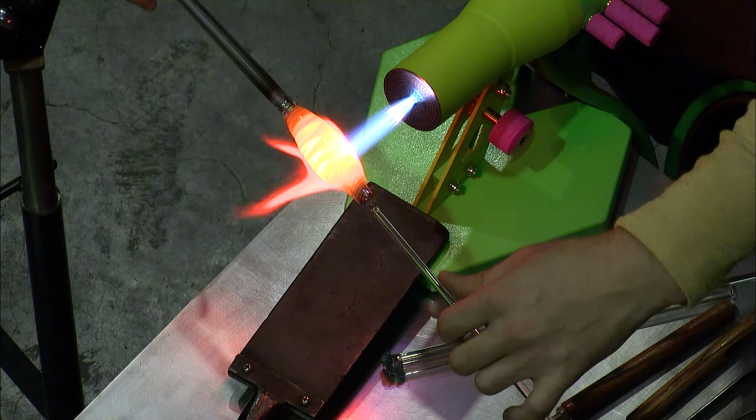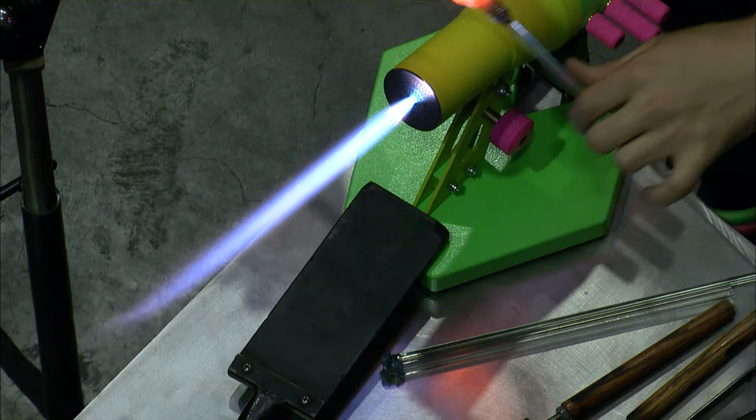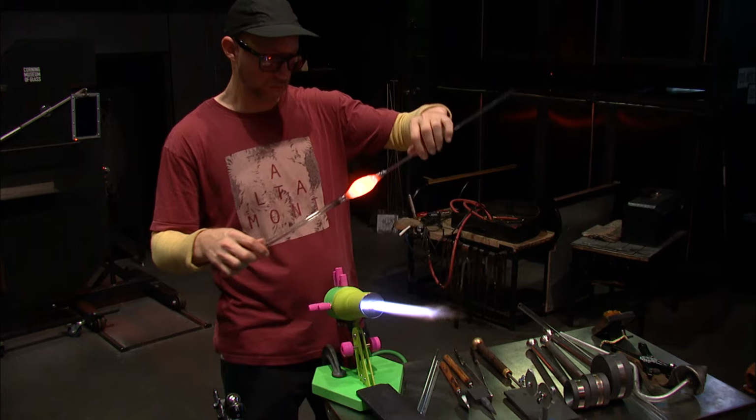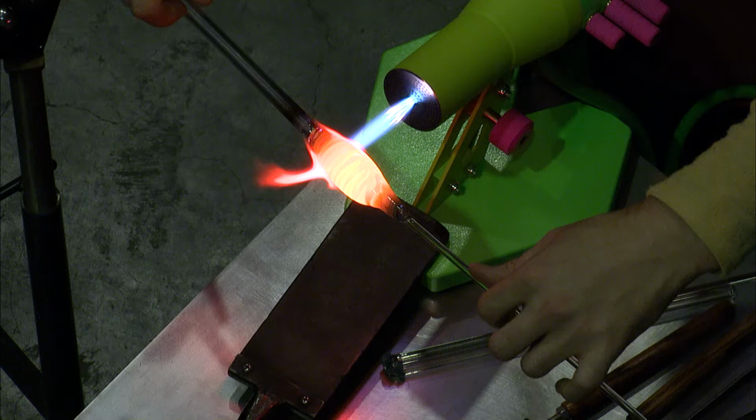Glass, as it's heated, swells or expands a little bit. As it cools, it contracts. The different compositions of glass expand and contract at different rates. The glass that Austin's working with, it expands and contracts a lot with temperature change. So it's a lot less tolerant to temperature change. If it's heated or cooled too unevenly, different areas expand and contract so differently, they pull apart and they crack. We call that thermal shock. Borosilicate glass does not expand and contract nearly as much as soda lime, so it tolerates temperature change a lot better.